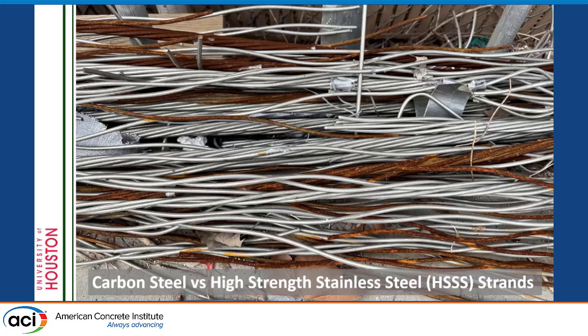Usually when I test specimens, I just put them outside of the lab and then try to get rid of them. But one day I was looking for something else outside of the lab, and suddenly I saw this picture, which shows both materials, the conventional carbon steel and the stainless steel. They were under the same condition, and you can see visually what happened to the regular carbon steel and the stainless steel, and that gives a reason why we are trying to study the stainless steel as a solution for